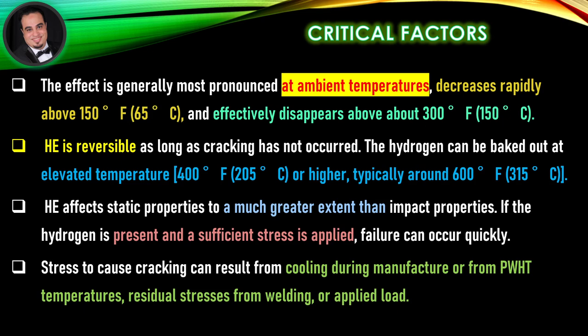Hydrogen embrittlement affects static properties to a much greater extent than impact properties. If hydrogen is present and a sufficient stress is applied, failure can occur quickly. Stress to cause cracking can result from cooling during manufacture, from post-weld heat treatment temperatures, residual stresses from welding, or applied load.